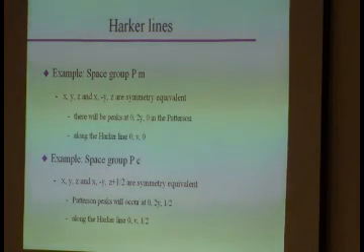Space group Pc, equivalent positions would be xyz, x, y bar, z plus 1/2. Same deal. You form the distance between these coordinates. Okay? Once again, we are in vector space, so you just subtract the x, the y, and the z component from each other. That means you'll get peaks at 0, 2y, 1/2. Once again, that's a line. Okay? One of the coordinates happens to be 1/2 now, but there's only one variable, the 2y. So you have a Harker line 0v1/2 along which you'll have peaks corresponding to every single atom in that unit cell with its symmetry equivalent atom.